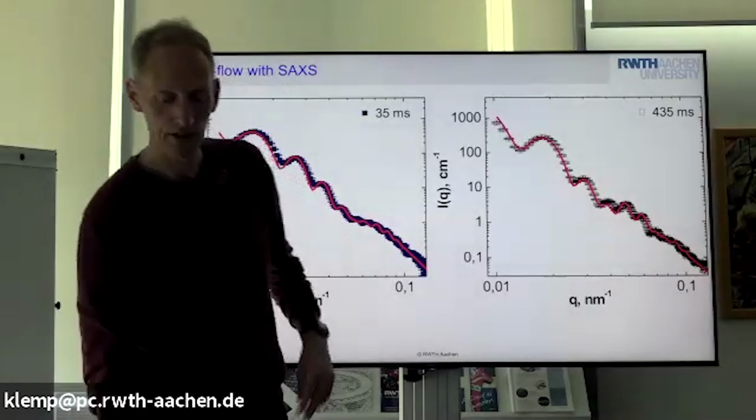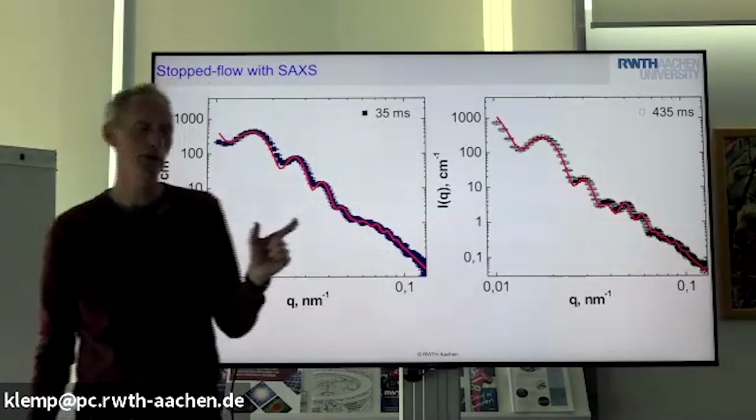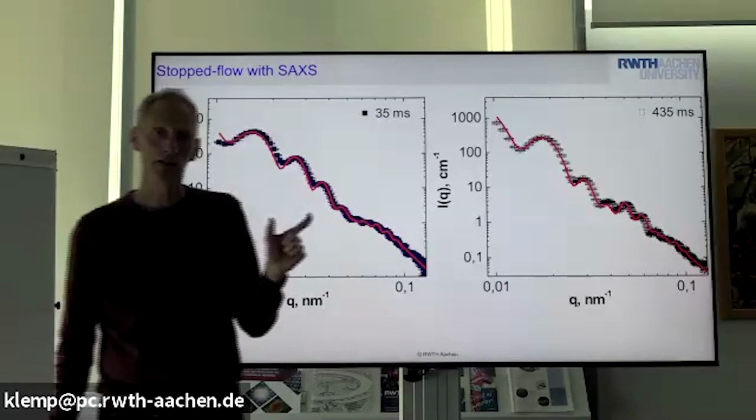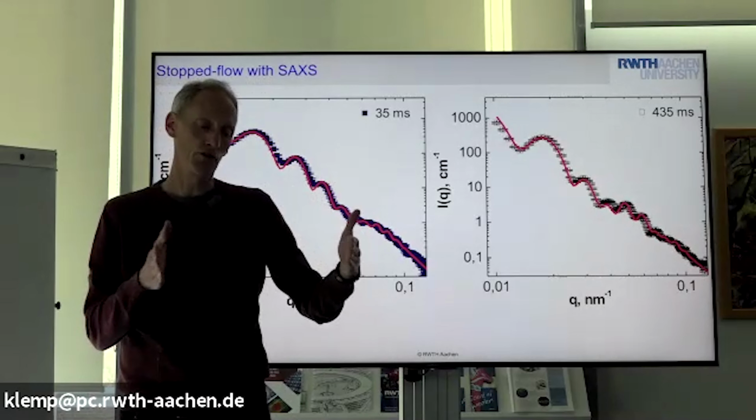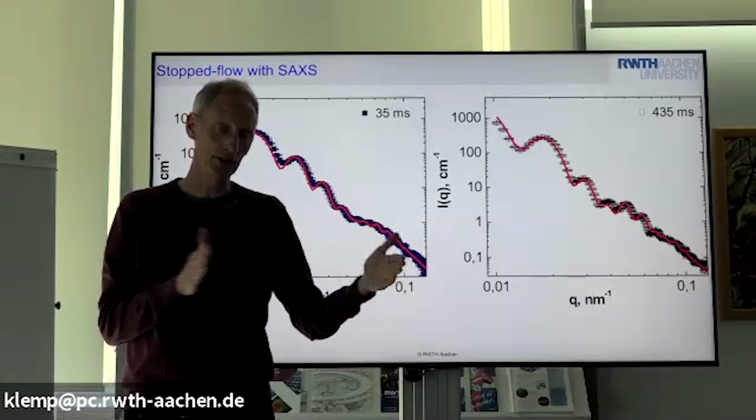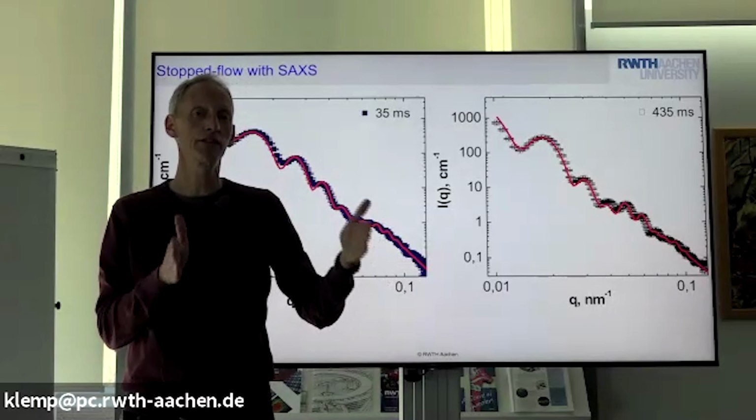Could you please comment further on the mechanism of colloidal stability of suspensions of the microgels when the outer layer or whole microgel is collapsed? Does charge now play a role, or are they still sterically stabilized? No, that's really a charge stabilization. The initiator we use is potassium persulfate, so it gives us charge groups. And this is also the reason why during the synthesis of the precipitation polymerization, they are stable.